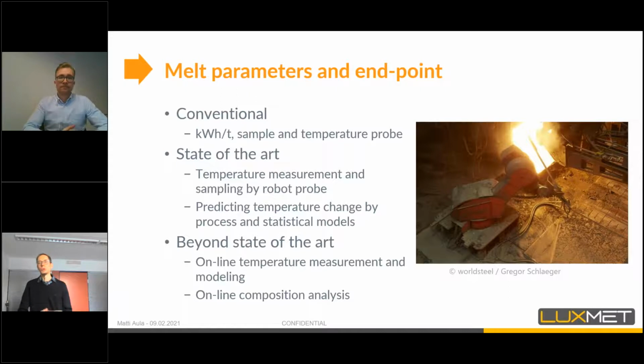And when the process nears its end, there is going to be a question of whether the melt is already ready for tapping. Now we are talking about what the melt temperature is and what the melt composition is. I think the most conventional method to do this is to get a sample probe, put it into the furnace and check the temperature. This is the conventional method.